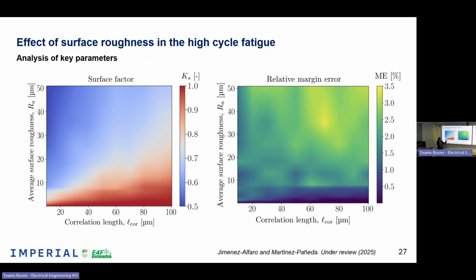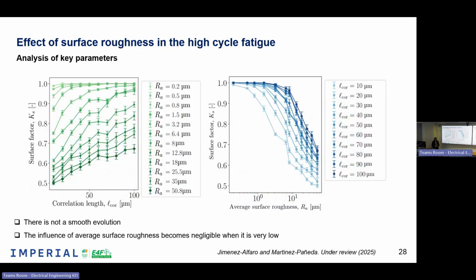As you can see here, it is bigger for bigger values of the average surface roughness and the correlation length. But looking at these numbers, it is always less than 5%. This is something we have done artificially. We have forced that we have repeated the simulation until we arrive at a maximum of 5%. So now we have also done the projections of this surface factor with respect to the 2 parameters.